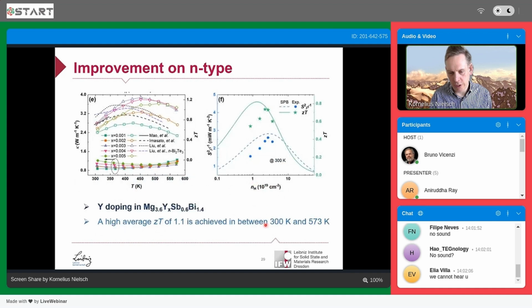Another strategy was to look at whether we can use different dopings to optimize the performance. In this case, we used yttrium doping. This also improved, for example, the mobility compared to using the doping of tellurium. And this was another small step to improve the average zT of the material to 1.1.